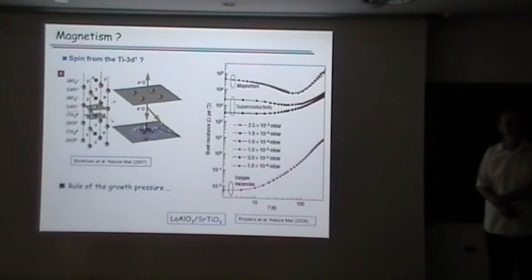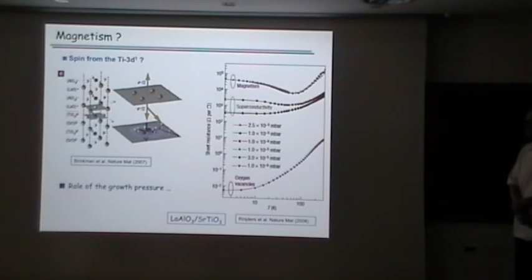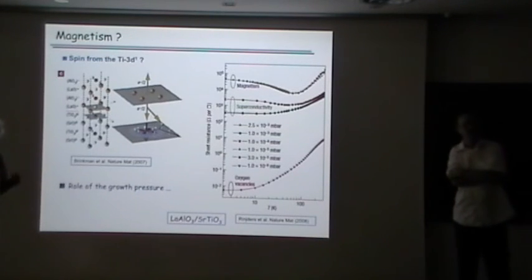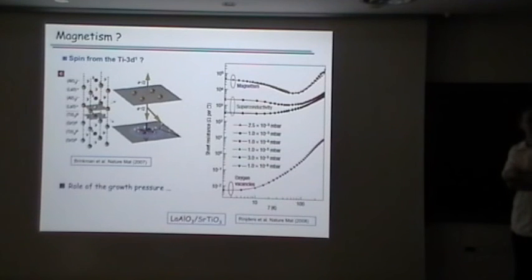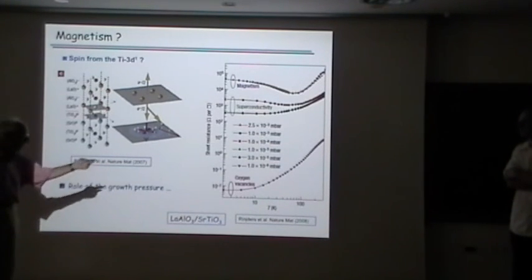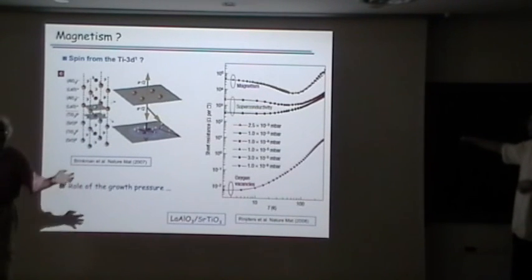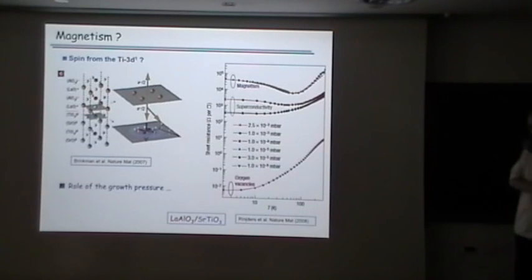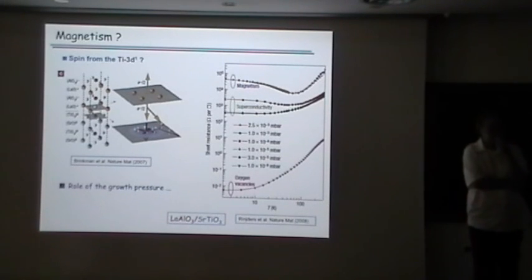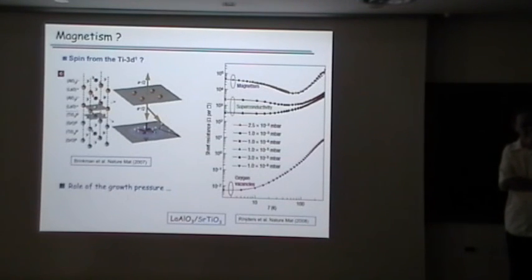But in a sense, actually, the picture of oxygen, for example, the one which George Zavadski advocates, that would probably give you the other way around, because they argue that it's oxygen vacancies which provide the mechanism. But then conductivity should be higher. Well, I mean, I think they would probably actually have to argue that it's clusters of oxygen vacancies. Right. Then it becomes much more detailed. Conductivity should be lower and not higher, because conductivity is oxygen vacancies. No, but I think the bottom curve, we all agree, is in some sense very different. Even when you're, I mean, there you really have something which is bulk. When you're dealing with, even with these carrier densities, the point is that they're small, but they're not that small. They're sort of 1%, if put in the 2D sense. That's a possibility. Yeah. The distribution of the oxygen vacancies.